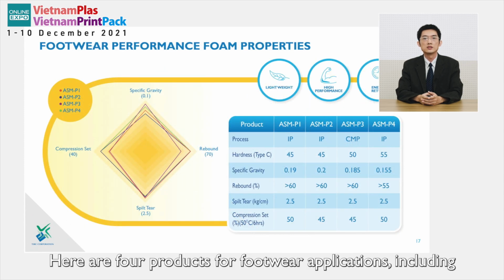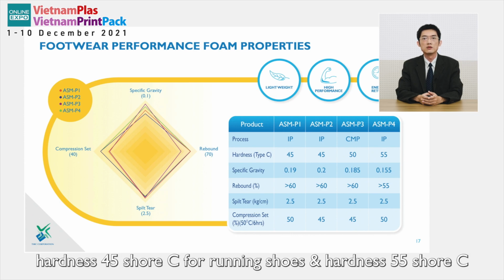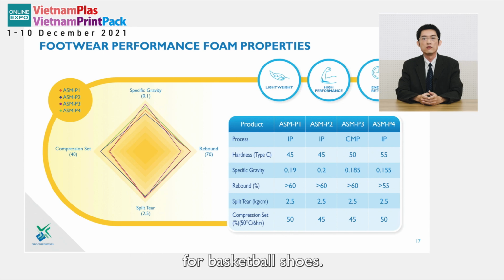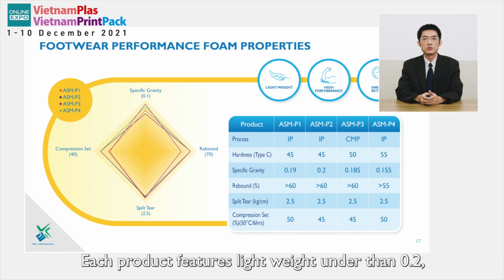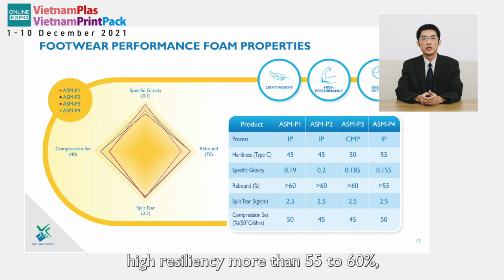Here are 4 products for footwear applications, including hardness 45 Shore C for running shoes and hardness 55 Shore C for basketball shoes. Each product features lightweight, specific gravity under 0.2, high resiliency more than 55 to 60%, split tear more than 2.5 kg per centimeter, and good compression set less than 50%.